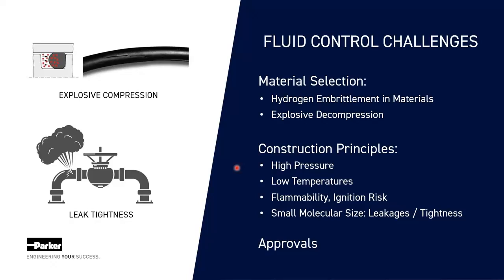To speak about the Joule-Thomson effect, not all gases undergo a cooling effect upon expansion. Some gases, such as hydrogen and helium, will experience a warming effect upon expansion under conditions near room temperature and pressure, which might impact the behavior of our safety shut-off valves and pressure regulators. To consider the temperature range on board of a vehicle, I already mentioned the ambient and media temperatures, which can go down to -40 degrees C and more on the cold side, but also reach maximum temperatures of +100 degrees C, which has an important impact on our soft seals.